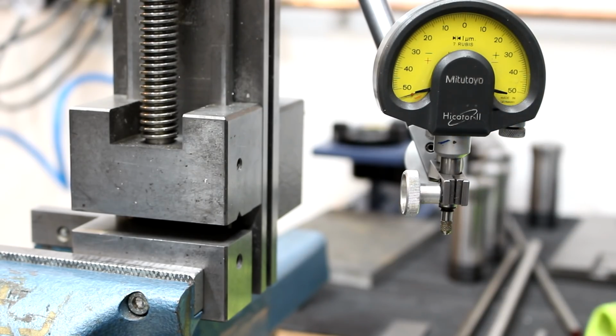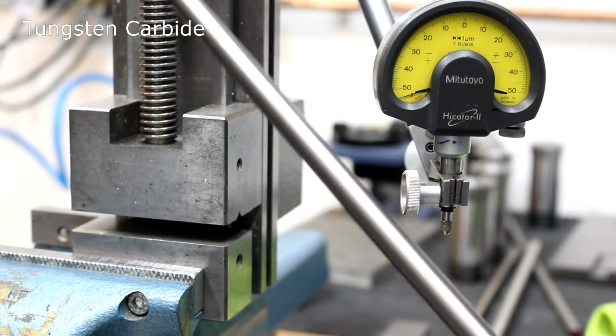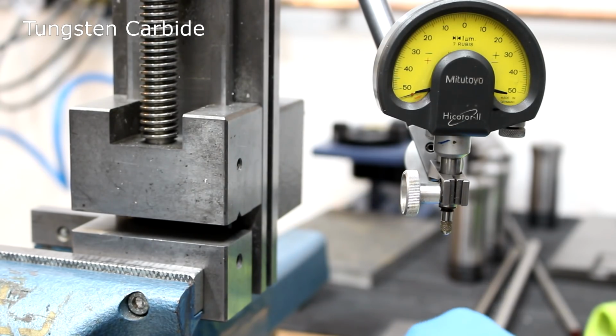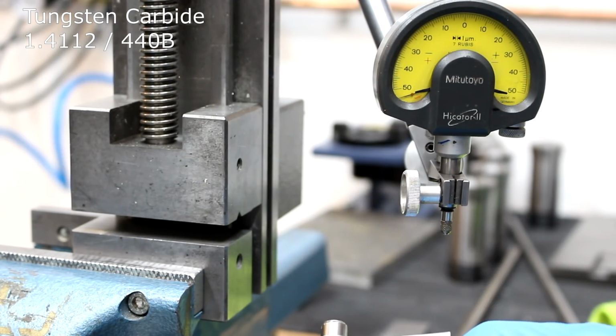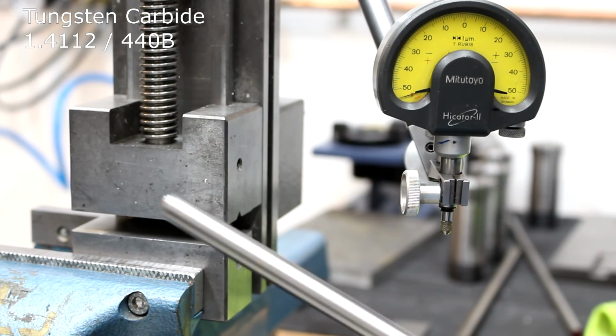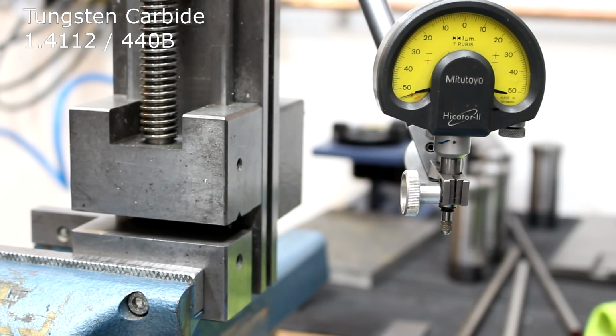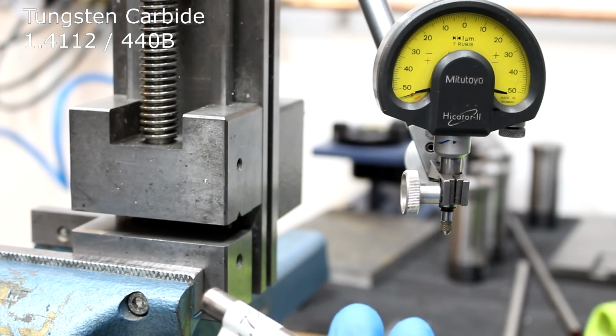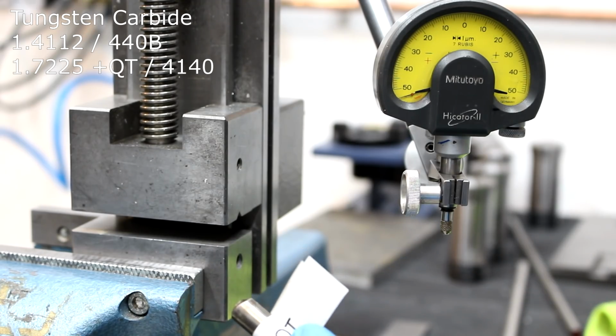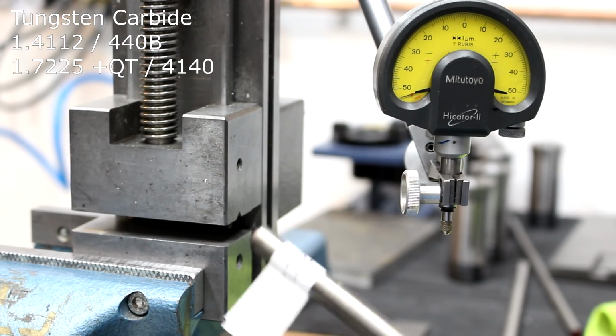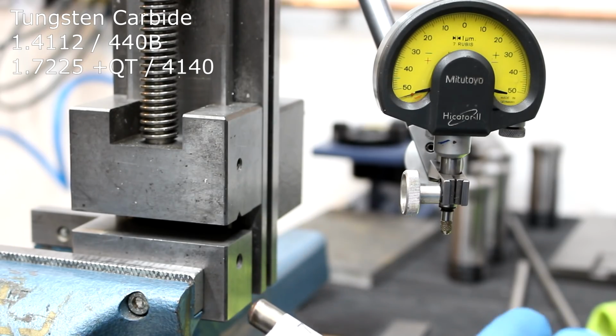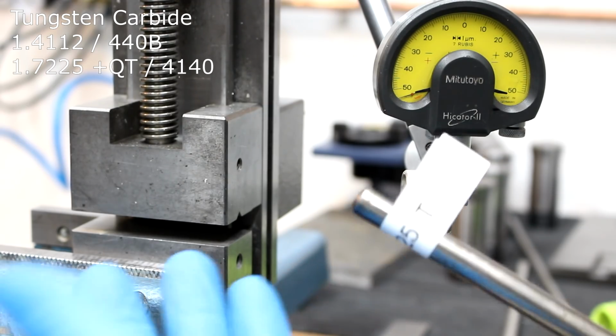And what we want to do here is compare the bending under load of 3 different materials. I have solid carbide, which is the material that we used for the boring bar. We have a piece of 1.4112, which is, I think, 440B stainless, which is a hardenable stainless steel, but it's in soft condition here. And I have 1.7225 QT, meaning quench and tempered. This is your basic 4140 chromoly in a commercial heat treat.